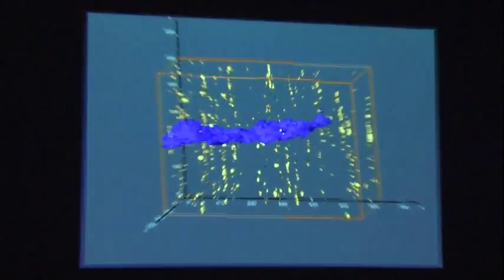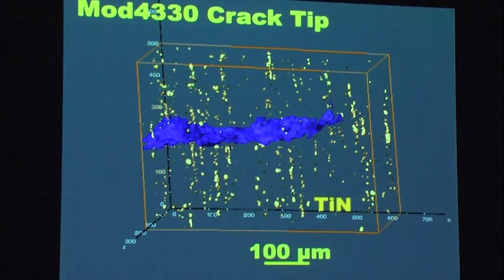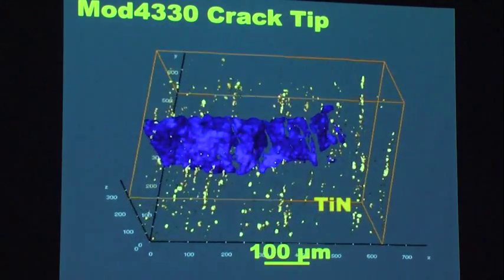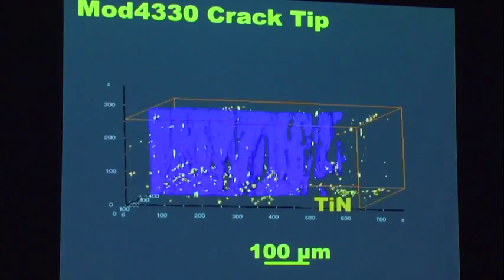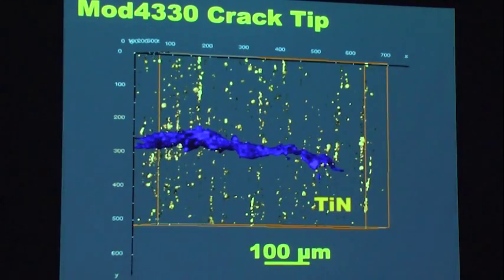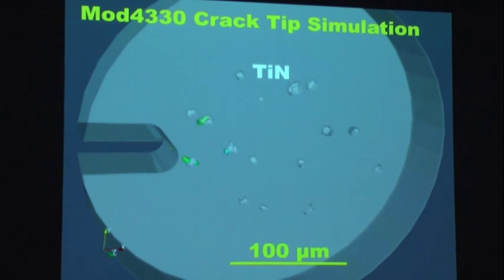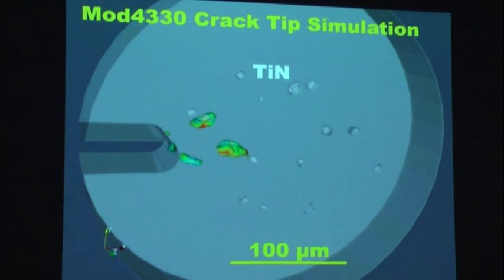And there, we've taken these crack tips apart by serial sectioning and by light microscopy reconstructed the process zone at the head of this, where you can see the partially intact material has a corrugated washboard type of structure that's coming from the shear localization from the fine particles accelerating the coalescence of the primary voids.